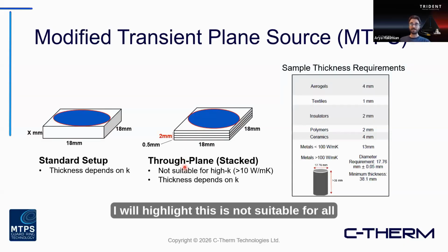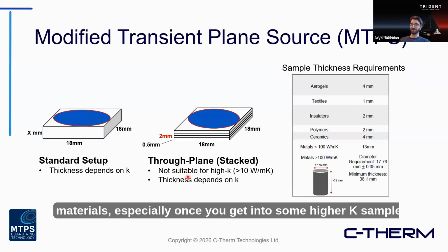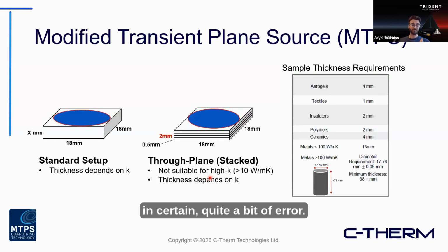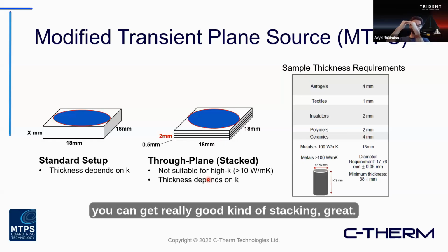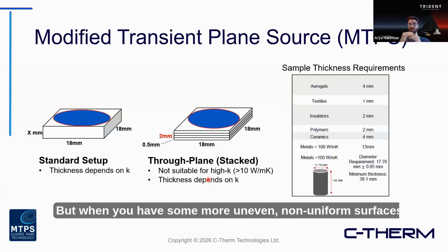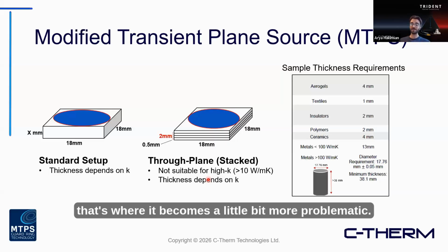Now, I will highlight this is not suitable for all materials, especially once you get into some higher K samples. The contact resistance between those layers starts to result in quite a bit of error. If the layers are very flat and planar, or maybe somewhat adhesive in nature, you can get really good stacking. Great, but when you have some more uneven, non-uniform surfaces, that's where it becomes a little bit more problematic.